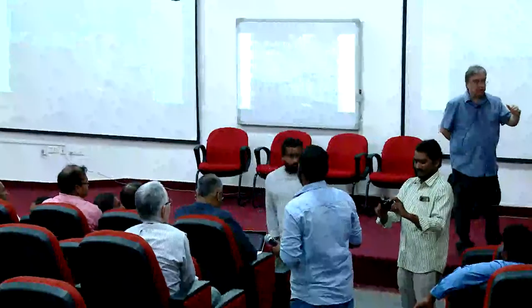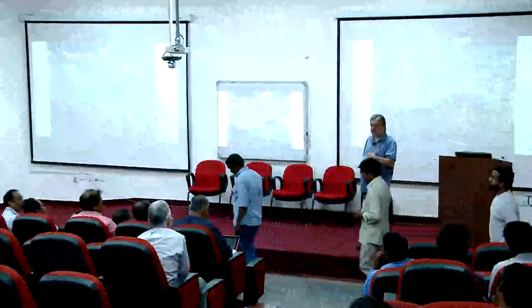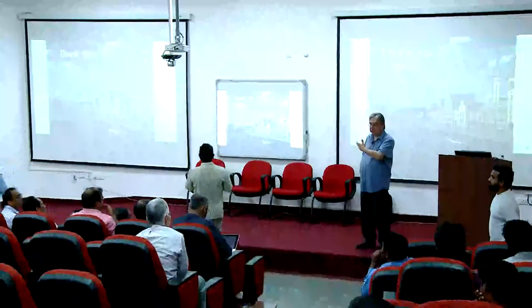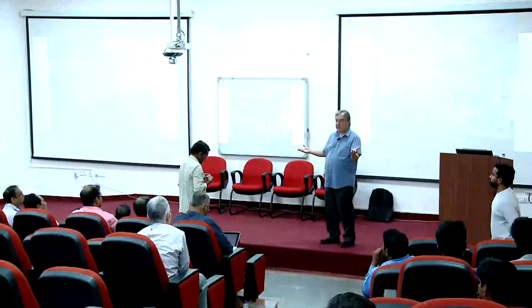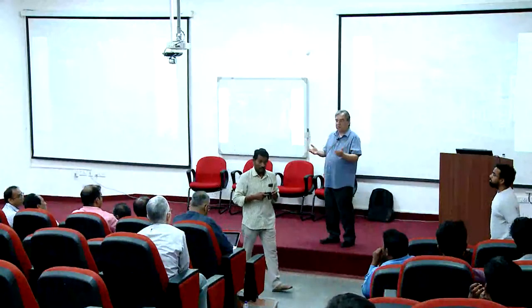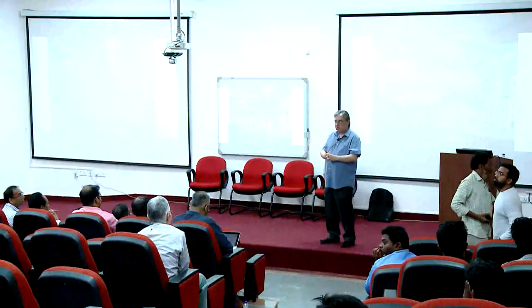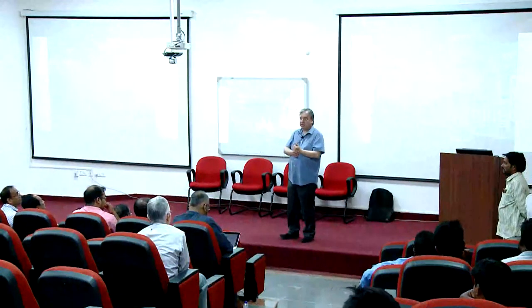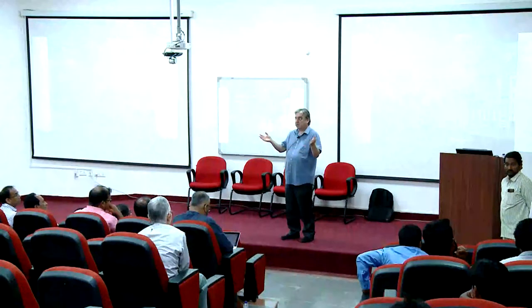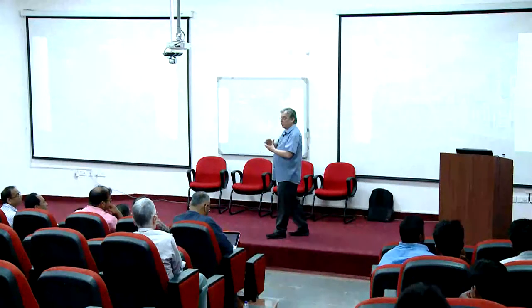Well, I only talked about RVE to say that for the rest of my talk I would not work with RVEs. So the RVEs that I showed here, the examples, they were not mine. We didn't work with RVEs. They were purely from the literature. But you're absolutely right, that's already the first question that's really part of the big problem. How are you going to make such an RVE? If you decide to do it in purely experimental ways, you want to have a 3D image of your microstructure. It's not simple. And even if you have it, you can never be sure: is it large enough, or is it too large, because calculation times will ramp up greatly.